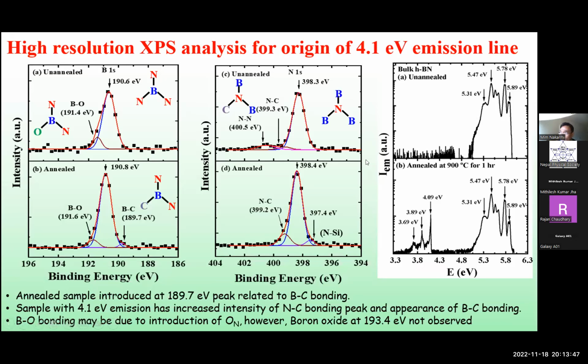But if the boron or nitrogen also has some carbon or some other element sitting nearby, then we will get some small signal or small peak from the XPS above or below that main core binding energy. So what we did, we investigated those two samples, one which has 4.1 eV emission and one which does not have 4.1 eV emission, and looked at what the difference is in the XPS signal.